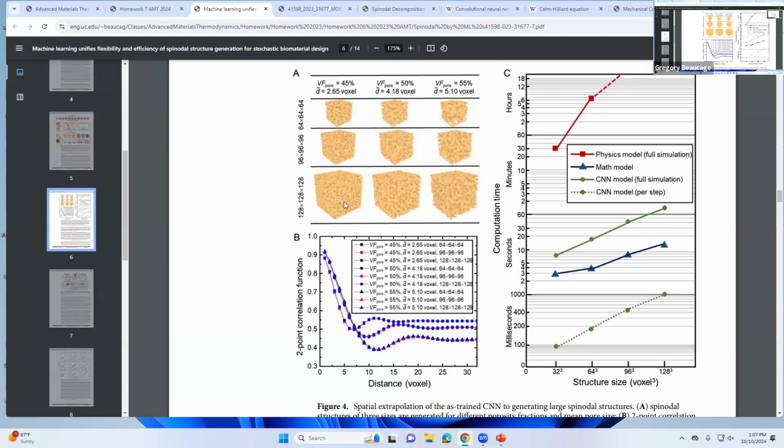So it's a double sum of the first point and the second point. A double sum of all the possible first points and all the possible second points. And you're going to do that as a function of R. You change the R and do it again. And so you're going to have, is it correlated or not? When you're at 0, it's like 100% correlated because you're at the same point. It has to be, right? You divide that by the density, so it should be 1 at 0.